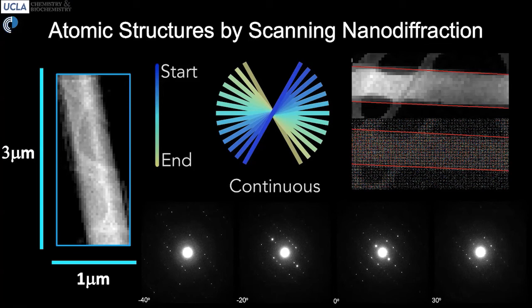So after we've recorded all of this data, we've tilted that crystal to various orientations in a continuous fashion. So we start at one tilt angle and we're rotating that crystal in the beam and scanning. And then synthesize or generate diffraction patterns that would ordinarily have been obtained using a selected area aperture, but now are obtained using an algorithm that detects where the best diffraction is in space from these scans. And we get what would be equivalent to diffraction patterns from this crystal at minus 40 degrees, minus 20 degrees, 0 degrees, 30 degrees, and so on.